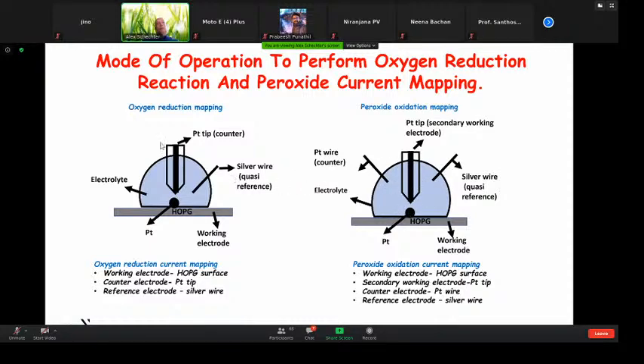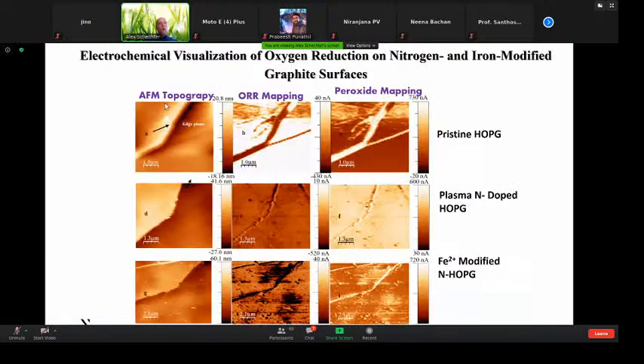So here's an example. On the top left side, you can see an HOPG, highly oriented graphite plane that was freshly cleaved. You can see an edge plane here. It's an edge plane of the graphite, and this is an AFM image. Now we can take the tip, and this is the electrochemical part, and scan to see where we have electrochemical currents. Here, the dark areas are where we're getting electrochemical currents from the surface. You can see that most of the current is coming from the edge plane, and perhaps some defects here.